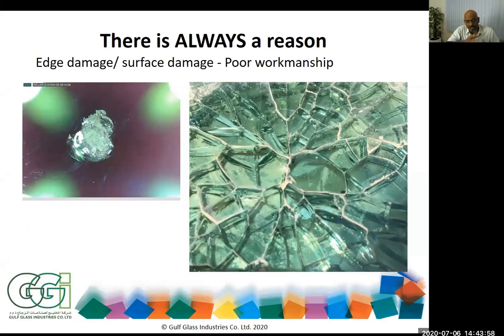The surface damage, this is under a microscope at nearly 10 times magnification, and you can actually see a spot. You can actually see the surface being damaged. And from this point, the glass would crack. When we investigated more, we understood that after the glazing was done on this 30,000 square meters of glass, on the top floor they were doing some concrete work, and the glass was taking in this concrete. It was just falling onto the surface of the glass. Everything was coming down with such high velocity and hitting the glass and creating these cracks.